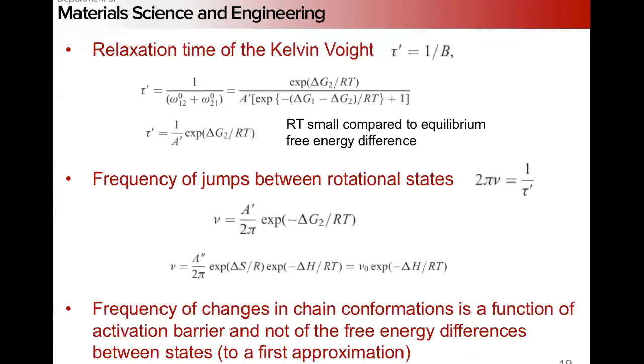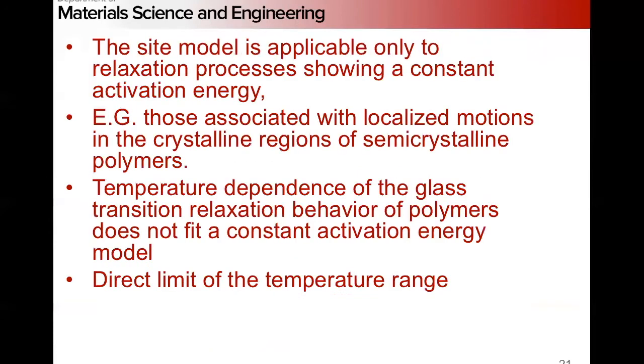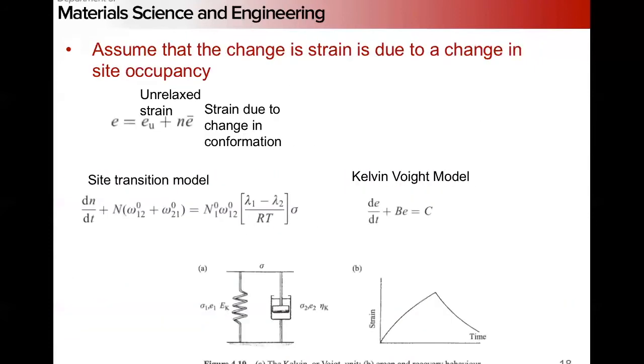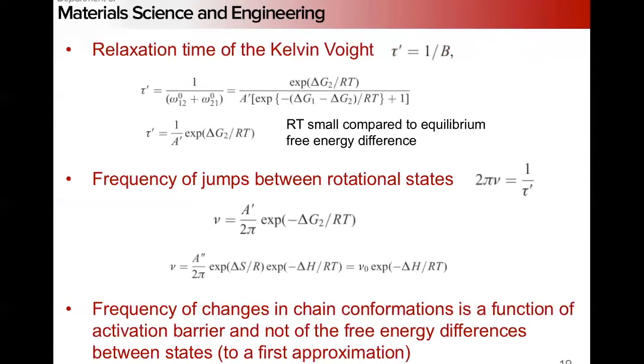And the relaxation time of the Kelvin-Voigt model is 1 over that B parameter. So if we have our equations that are of the same form here, our B parameter looks kind of nasty like this, with these exponentials and the difference between the activation energy. But if we assume that our gas constant times temperature, RT, is small compared to the equilibrium free energy difference, we simplify out to something, again, that looks pretty familiar. Nice exponential relationship, right?